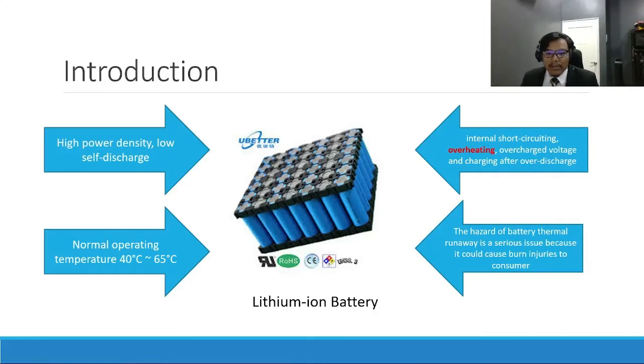Continuing about lithium-ion battery, it is a popular energy storage method because it has high power density and low self-discharge. And a normal operating temperature for lithium-ion battery is 40 degrees Celsius until 65 degrees Celsius. But lithium-ion battery can be damaged by internal short circuiting, or overheating, or overcharge voltage, or charging after over discharge. This is dangerous because the lithium-ion battery can pose a hazard of battery thermal runaway, which is a serious issue because it could cause burn injuries to consumer.